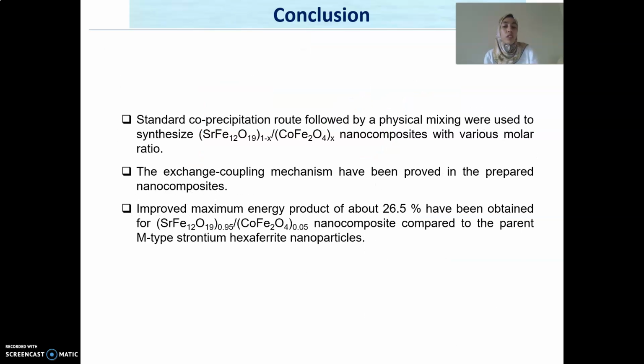As a conclusion, the standard co-precipitation route followed by physical mixing was used to synthesize the nanocomposites. The exchange coupling mechanism has been proved in all nanocomposites, and an enhancement of the maximum energy product of about 26% was obtained for 5% of the soft phase.